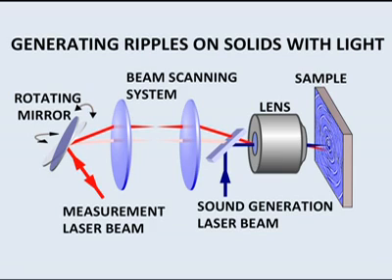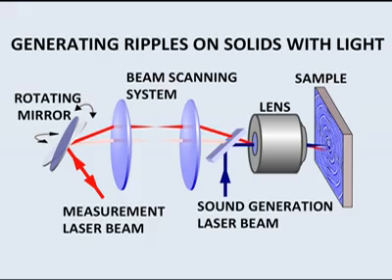We experimented with sound in microscopic gratings. Structures like this are called phononic crystals, whose acoustic properties have been engineered to vary periodically in space. In the experiment, blue laser light pulses create tiny sound ripples by heating a small spot. Infrared light pulses detect the ripples. The sound pitch is very high, around 1 GHz, with amplitudes in the picometer range. We scan the detection point and change the timing of the laser pulses to make movies of the ripples using interferometry.